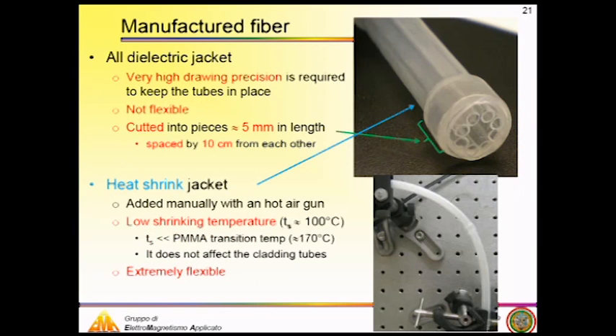Another improvement for our waveguide was that, instead of using dielectric cladding over the entire length of the fiber, which gives some problems because this jacket is very robust and so not very flexible, but we want a flexible waveguide, we decided to cut it into pieces 5 millimeters in length and put them 10 centimeters apart from one to the other. This allowed us to keep the tubes in place but without affecting the flexibility of the fiber.